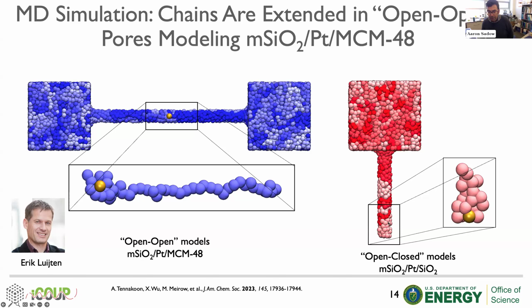closed end, and the product has to diffuse out through the pore that's covered with polymer already. And that can keep it close to do additional cleavage, what we call overhydrogenolysis. So the idea behind this porous core, and what's illustrated nicely in Erik Luijten's simulation, is that when you do a cleavage here, now the product can move away, and the chance of it coming back and undergoing a secondary cleavage to give lower molecular weight species, and those are the things that lead to gases that we don't want to make.